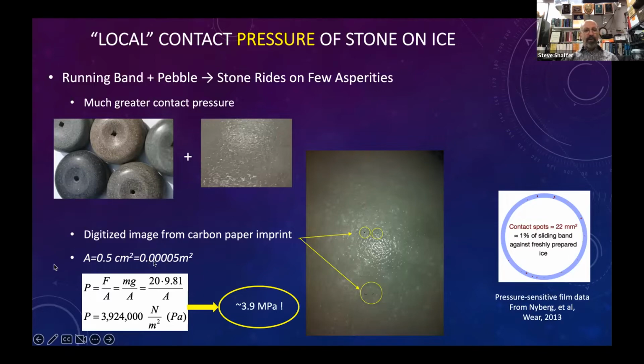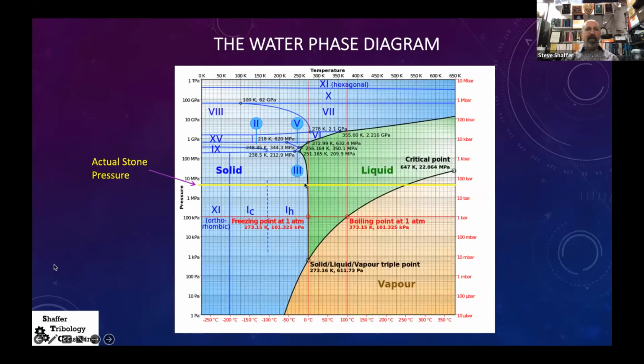two orders of magnitude smaller, 0.00005 square meters. And our colleagues over in Sweden at Uppsala, they used some pressure sensitive film, and they found that the contact spots were about 1% of the sliding band. And this number here is about 2% of the 0.002 we measured before. So we're in the same ballpark. And when we use those numbers, now we're at about 4 megapascals. So now we're way up here on the curve for the actual stone pressure on each asperity contact.